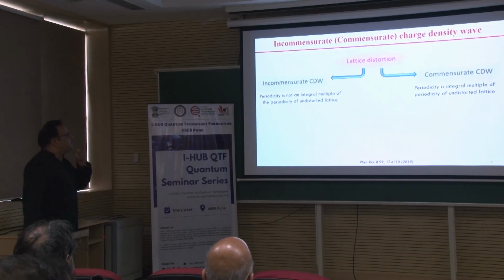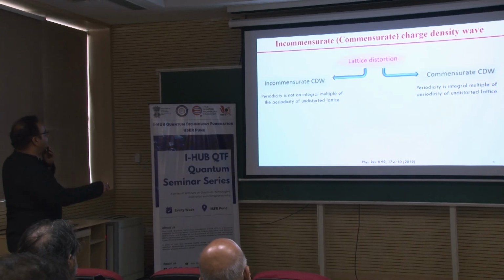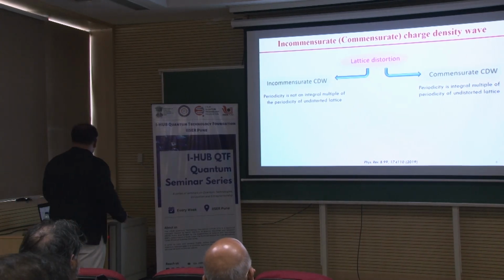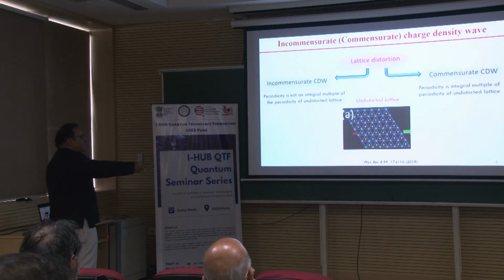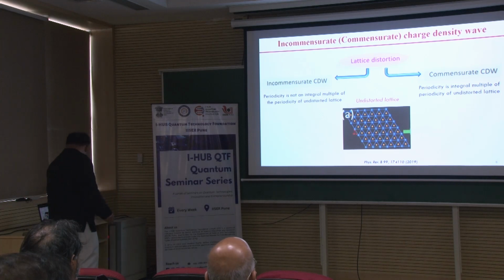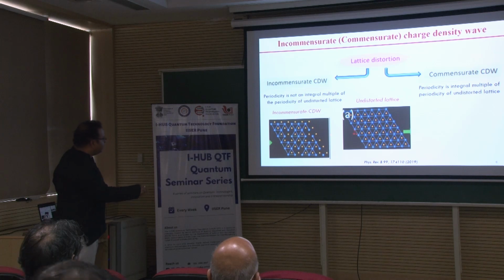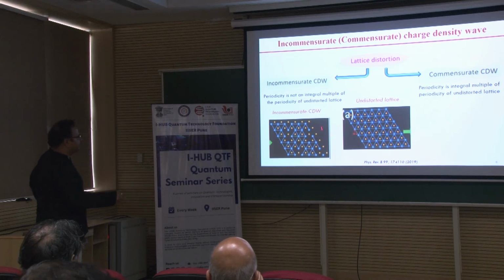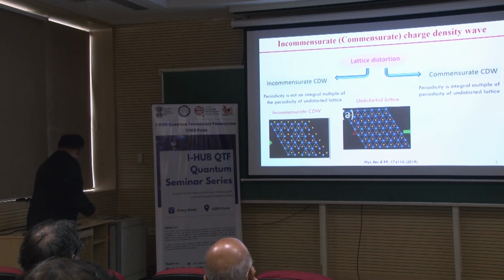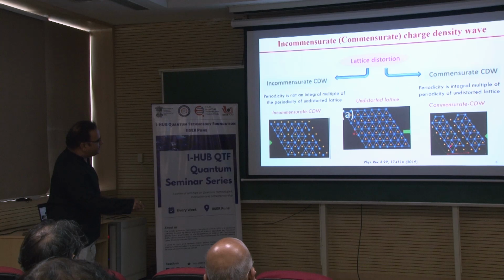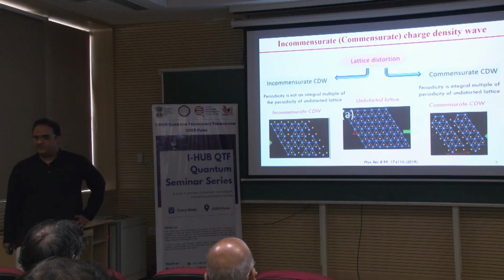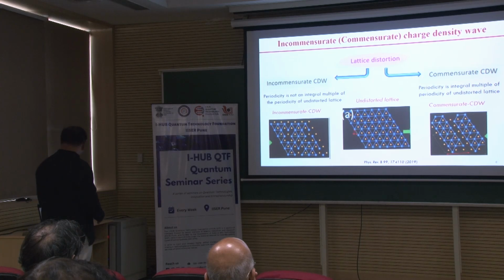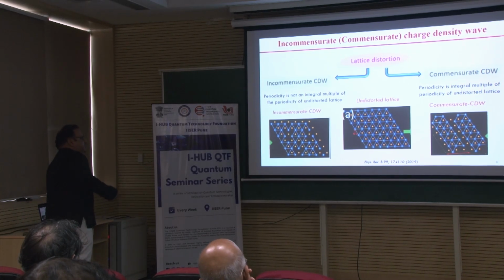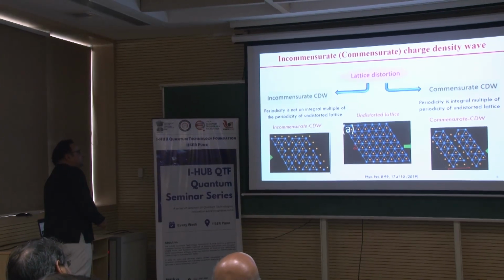Let me tell you how you classify the charge density wave. You can classify charge density waves as commensurate and incommensurate, based on the periodicity of the undistorted lattice. Let us say this is the undistorted lattice with the periodicity of A. If the new lattice, which is reconstructed because of the charge density wave, does not have a periodicity in an integer multiple of A, you say it is an incommensurate charge density wave. If the periodicity of the newly constructed lattice follows an integer multiple of A, then you say it is a commensurate charge density wave, and this is how you can classify different charge density wave materials. Some of the materials show both kinds of charge density waves. So, these are the lattice instabilities which show the incommensurate charge density wave.